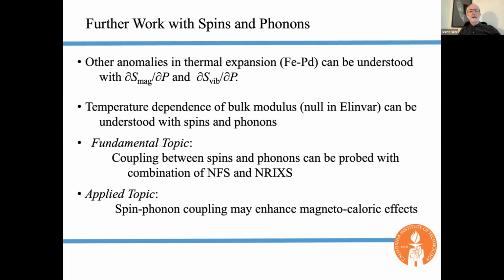We can look at other anomalies in thermal expansion in magnetic materials, of course. The temperature dependence of the bulk modulus, which is null in Elinvar. I think we got data on that that look good. And we can look at spin-phonon coupling here fundamentally, or maybe how we can enhance magnetocaloric effects by coupling into the phonon bath.